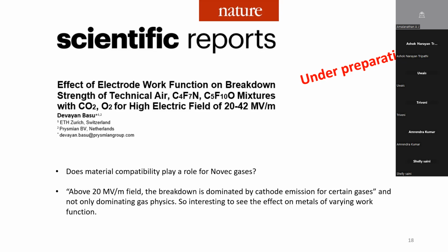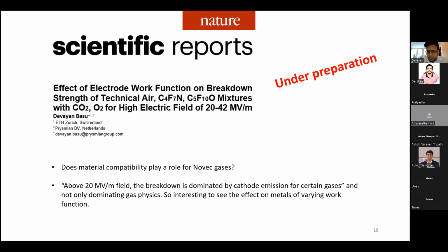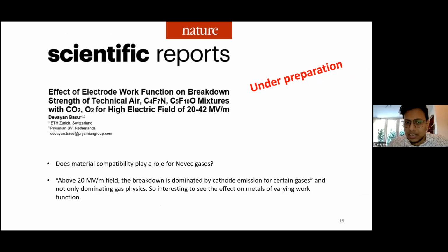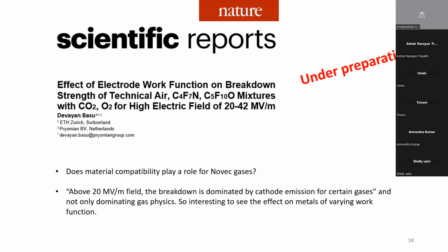So for this one, we see the effect of the work function for C4, C5, and technical air mixtures with CO2 and O2, which are the buffer gases, but for high electric field of 20 to 42 megavolt per meter. And we'll see why high electric field. As I said, the first question that appeared to me was, does material compatibility really play a role for Novec gases? And in the literature, it says above 20 megavolt per meter field, the breakdown is dominated by cathode emission for certain gases.